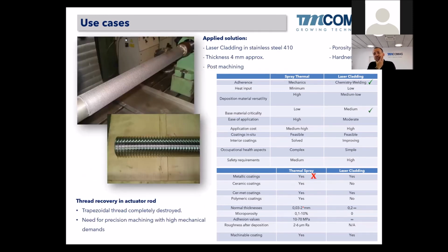Another example of laser application. In this case, our customer had an actuator rod with an ACME profile thread. It's a rod that has a thread machined along all the length, and it is used to actuate a valve gate. The customer had a problem with the thread, and he destroyed the thread completely. It caused a breakdown of the plant during the weekend, and we had to repair the rod. It's a special steel, a heat-resistant steel, so we couldn't find a new steel rod to machine.